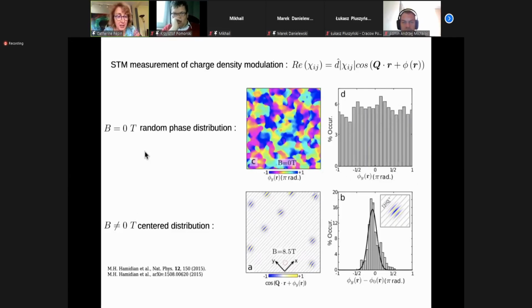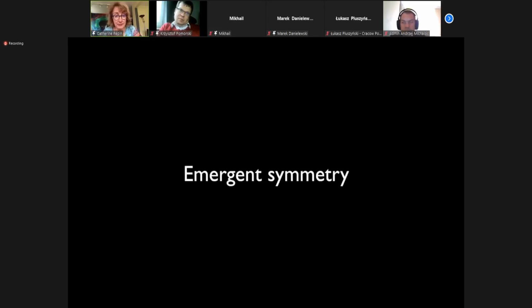Now when they subtract 8 Tesla and 0 Tesla, you see the vortices and the charge modulation inside. But very strangely, the phase slip becomes ordered, and this is on a very long range, basically the size of the sample. Namely, the amplitude of the charge order is short range, but the phase is long range. How about that? This is something that you have never seen anywhere. It's very unusual: the phase has roughly two orders of magnitude longer correlation range than the charge.